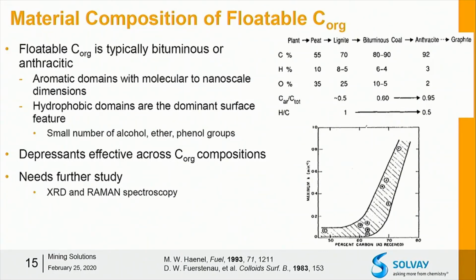type of material. And actually looking through the literature and looking at people who have actually characterized the carbon in sulfide ores, you tend to see it falls into a fairly narrow range of bituminous or anthracitic carbon. And this means that it has aromatic domains in the molecular to nanoscale. Hydrophobicity is the dominant surface chemical feature. There are oxygen-containing functional groups, but there tends to be a small number of them, alcohols and ethers or phenols mostly. And so it's not really clear how much material composition really matters in sulfide mineral flotation. And I'd really caution that it has been used as a crutch to ignore very valid mineralogy factors in understanding carbon flotation. I think it needs further study. XRD and Raman are the techniques to use. But I think it's important to at least recognize that.